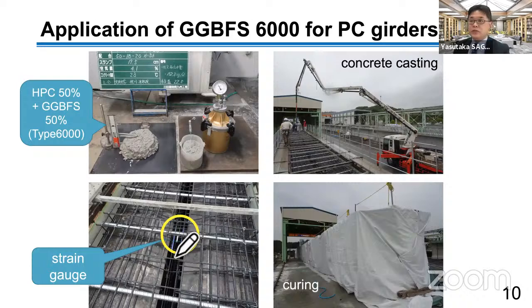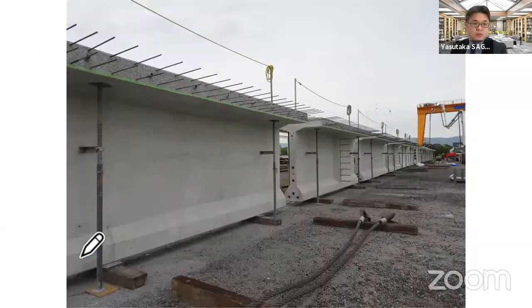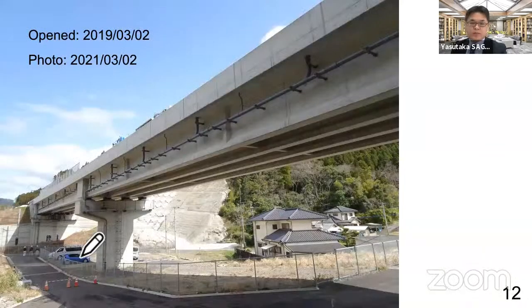The other application is GGBFS 6000 for PC girders, prestressed concrete girders. In this application, high early strength Portland cement 50% and slag 50% is used. In this case, some strain gauges are introduced to measure the shrinkage for monitoring. The girders consist of some precast segments. They are transported from the factory to the construction site, and then they are connected by the post-tension method. It is a two-span bridge.